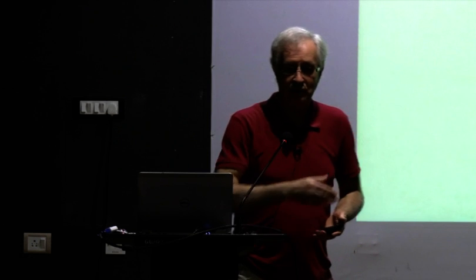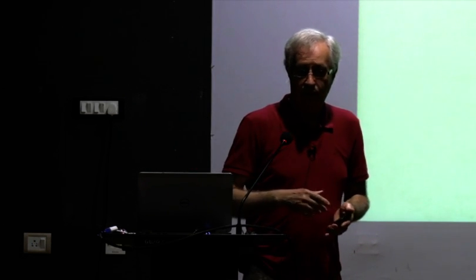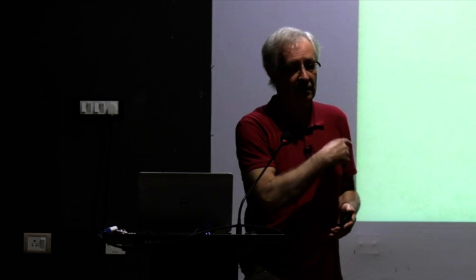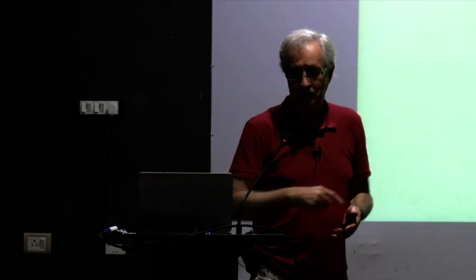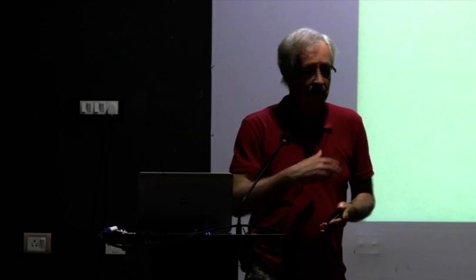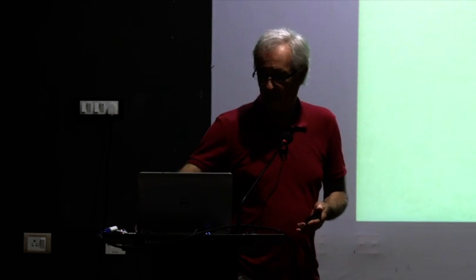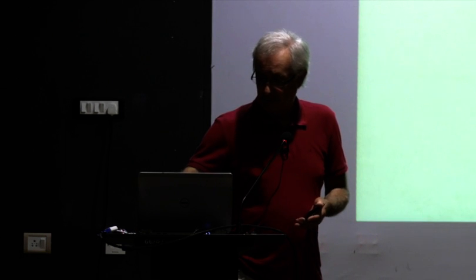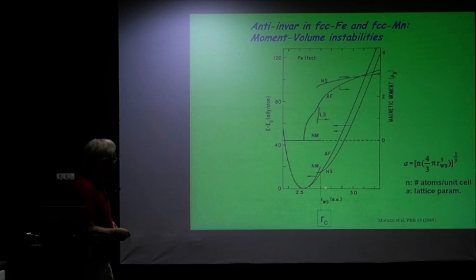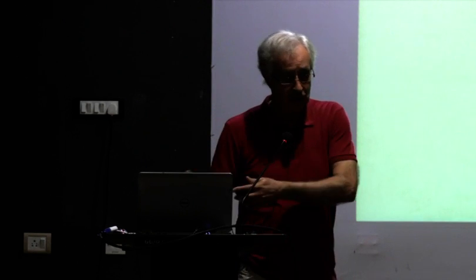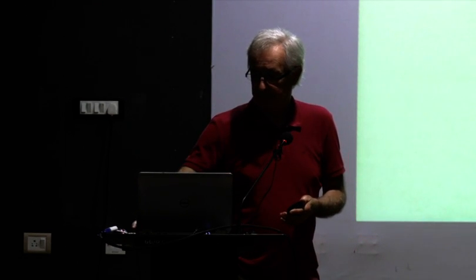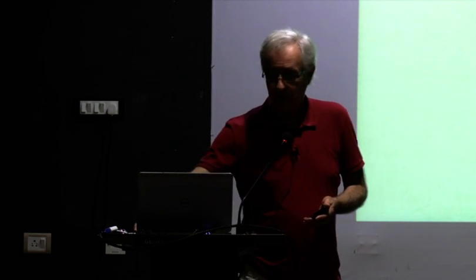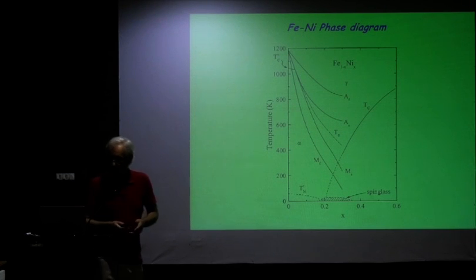So these calculations, back in the 1980s, of course have been improved, there are better calculations now, but for teaching purposes these diagrams are good, they give you a better overview. And in the case of iron, if it goes into the high spin state, the high spin state has a magnetic moment much higher than 2.2 mu B. It goes to about 2.5. We're going to see these experimentally as well. So, normal means this.